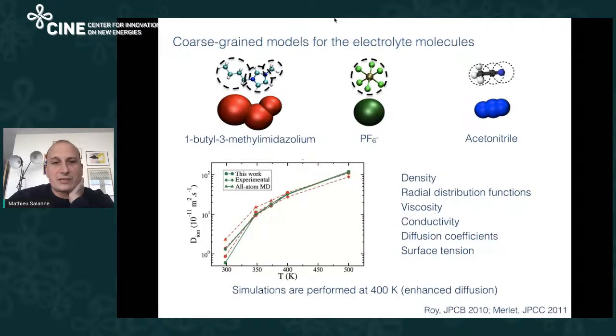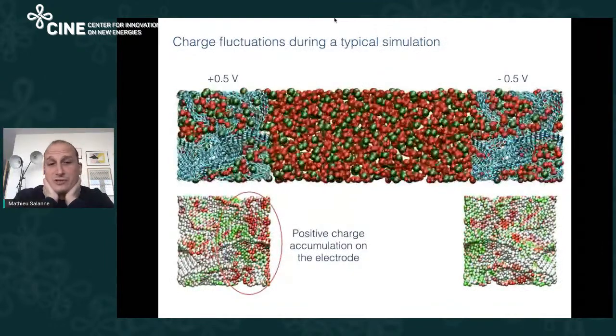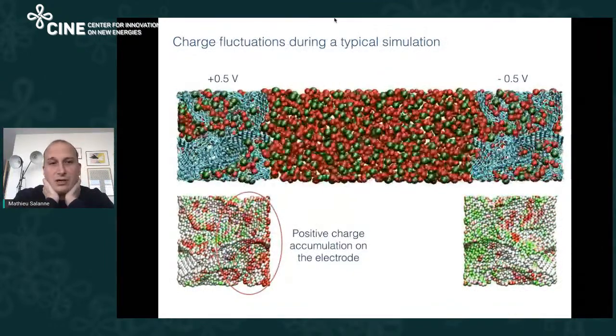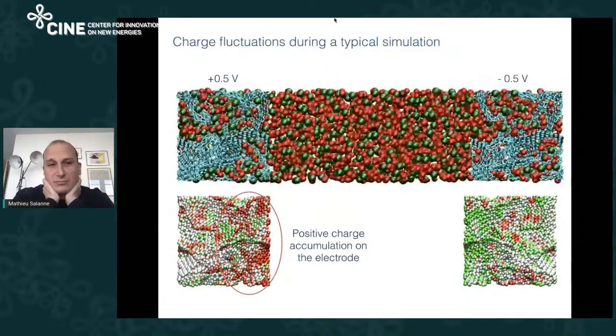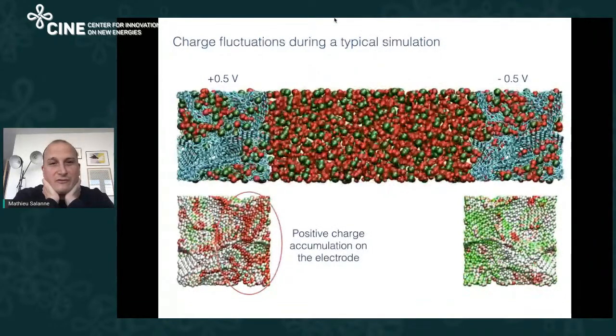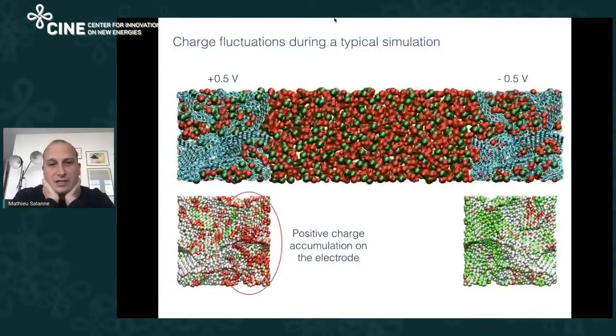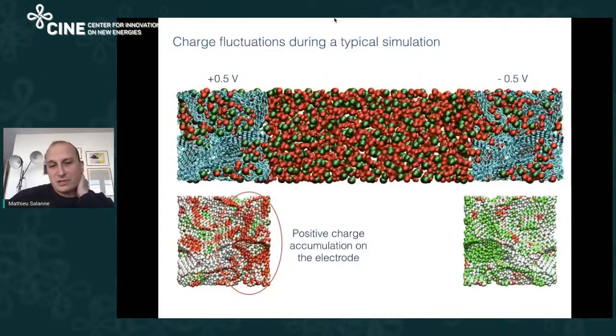So now, once we had these tools, here is an example of the first simulation we made. This is a supercapacitor with carbon electrodes that are at 0.5 volts and minus 0.5 volts. And you see that during our simulation, the liquid is moving. And in the meantime, we can also see how the charge is accumulating inside the electrode. So you can see here on the left that you start to have positive charge. On the right, you have negative charge. So this is the red and the green colors inside the electrodes. And well, since then, we have been working with these models, trying to improve them and trying to understand what's occurring.